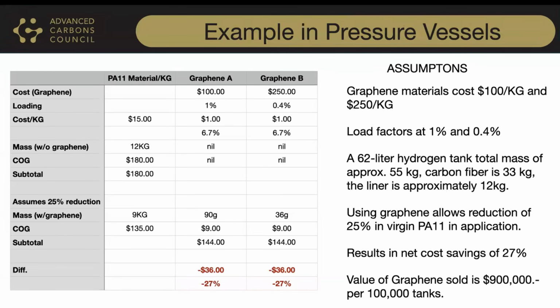And the net result that we see is that there's actually a cost of goods savings by adding graphene, even though it's at $100 or $250 a kilo. The customer in this particular case is actually saving $36 per unit, or a 27% savings on cost of goods for this component. So that's one example where you can actually add this material, get a better performance, and reduce cost at the same time.